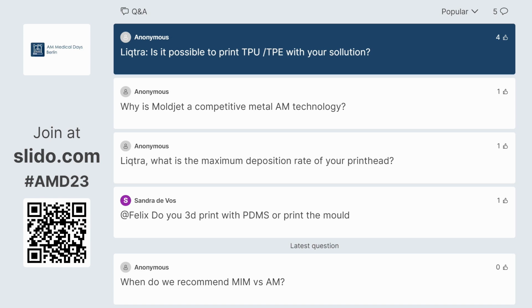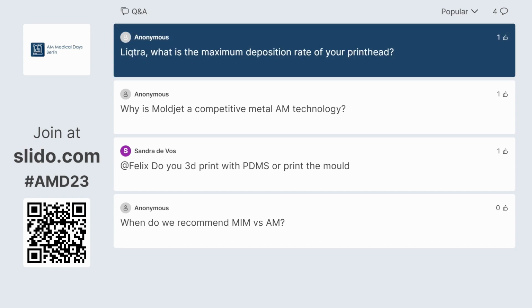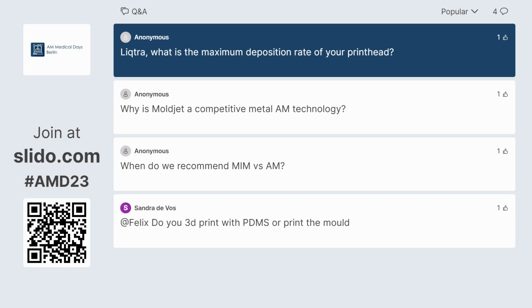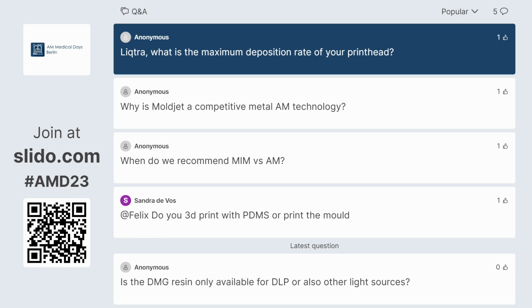Yeah, let's add another question. What's the maximum deposition rate of your printhead? So theoretically, 8 times as much as you can put through a regular printhead, because we have an additional nozzle for support material. But this is theoretical. If we go on large nozzles, 0.8 nozzles, and we have 7 of them, we run into problems of getting the heat away. So these parts are printed with 0.6 millimeter nozzles, and they reach deposition rates of almost 100 gram per hour, which is a lot for polypropylene. Also taking into account that polypropylene is very light, low density. This is a lot. I mean, throughput theoretically is much higher, a few hundreds.